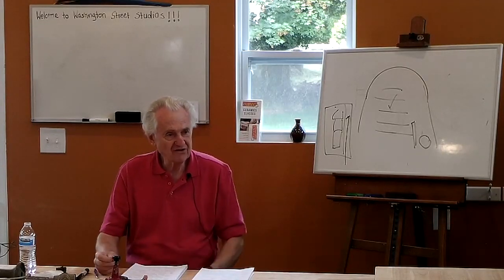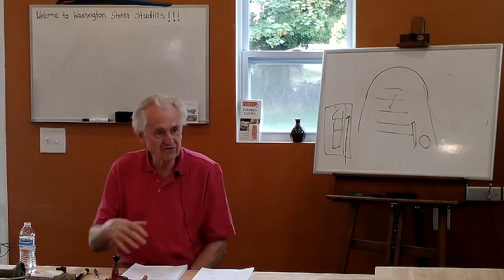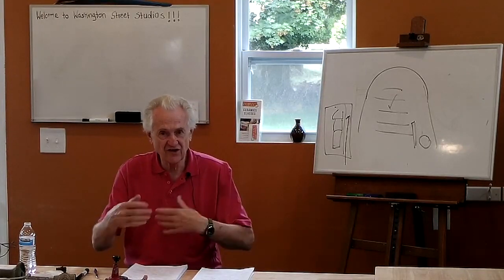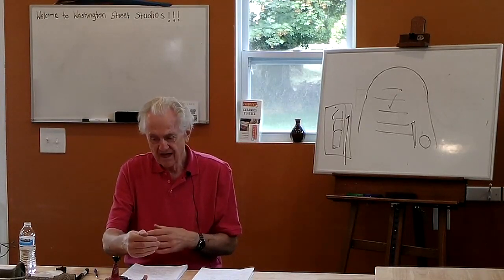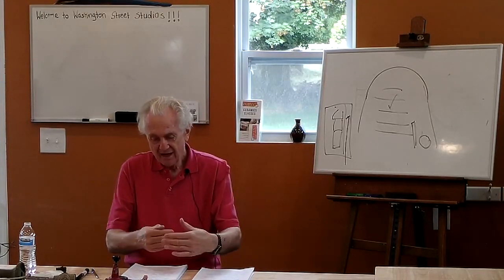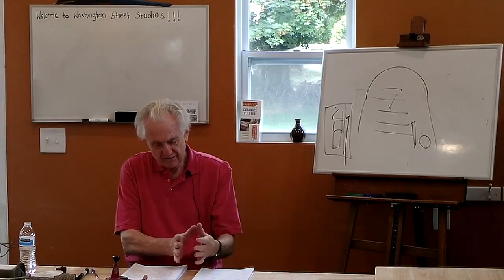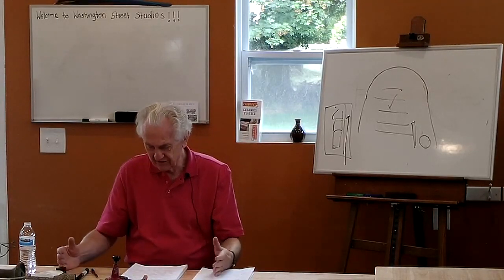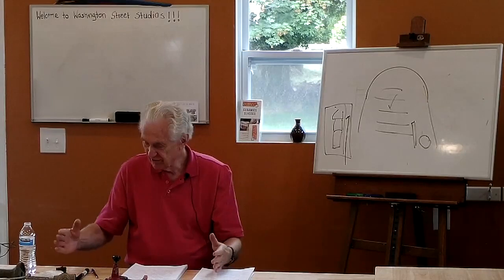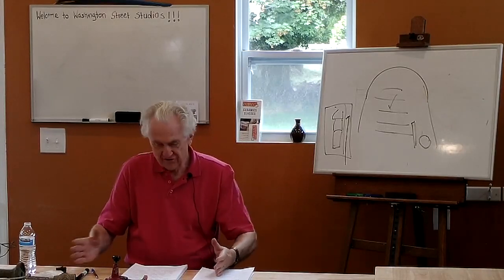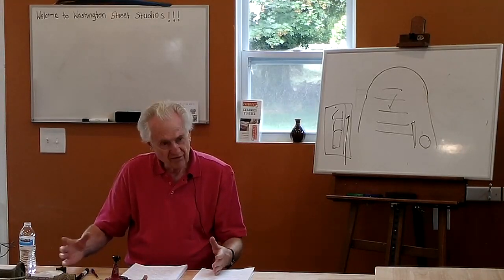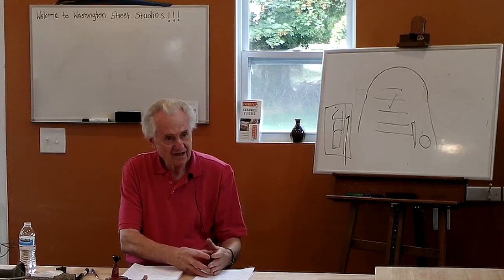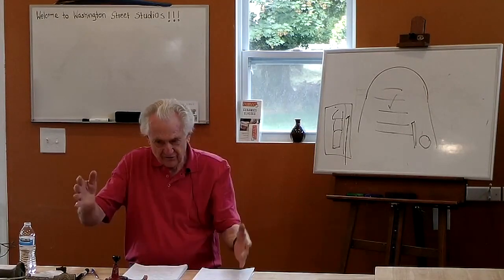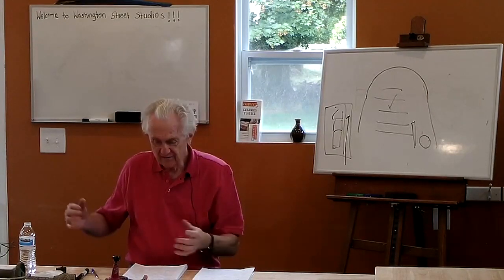It was a bad design on the kiln. It was a homemade kiln, and they didn't design it properly for a small kiln. And so to help fix it, I put in a tunnel, and I backed the burners out from the kiln, and I made about a 2-foot long tunnel. And I put the burner at the end of the tunnel, so that I had this 2-foot tunnel before it even got into the kiln. And that was because this was a really tiny chamber, only about this big. So the flame and everything would go right through it.